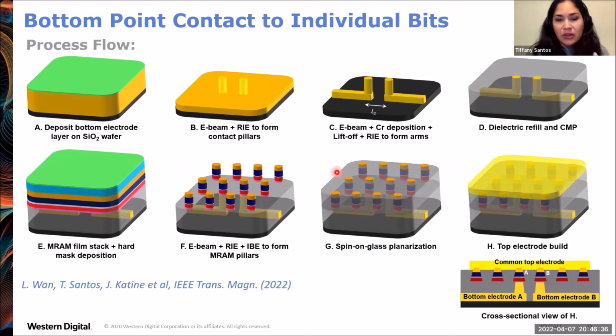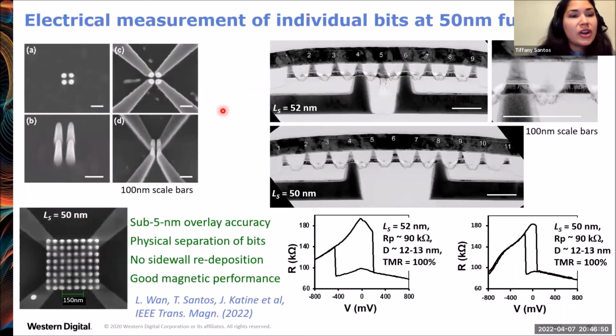We did a fill with a spin-on glass for planarization, and then put a common top electrode, so that schematically this is what the cross-section looks like, but then I can show you with real images here. So these are SEM images here on the left of the individual bottom point contacts, and then the contact leads. And then the tight pitch MRAM bit array is fabricated on top of the contacts. And then if we take a diagonal slice right here, then we get the cross-section TEM images shown here.